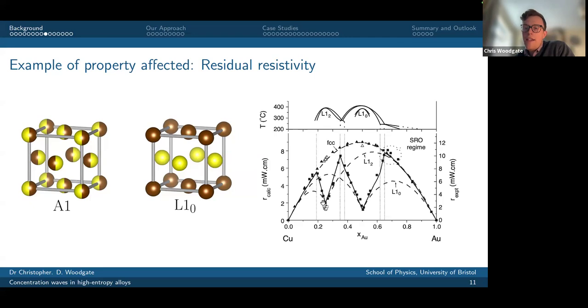But if I look at the squares, these are samples which have been annealed. So they've been baked at a particular temperature below the disorder-order transition temperature. What I'm seeing is either L10 at the 50-50 composition or L12, which is a cubic related structure, appearing. And there I see that my residual resistivity drops quite substantially. It doesn't quite go to 0, presumably because the material never gets perfectly ordered, but it drops a long way. And so this is an example of how the arrangements of atoms in an alloy can really affect their properties.